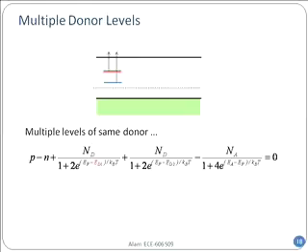So, if they have equal amounts of doping, then I have Nd, but you see I have an Ed1 in the denominator of the third term shown here in red. That goes with the donor level of that trap, right? What about the blue one? Well, this time I have another term, which is the second term, in which I have Ed2, because the electrons have to jump from the blue level to the conduction band. So I will have to introduce another term here, right?